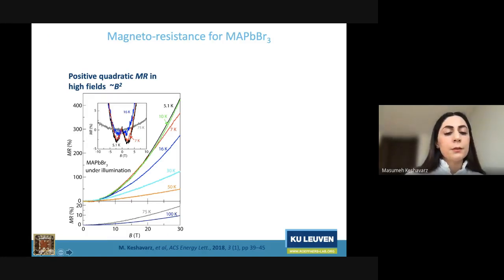Now let's look at the magnetoresistance as a function of field. In general, we measure the magnetoresistance for different temperatures. For methylammonium lead bromide, it is shown here, and we see this classical orbital effect, which is the quadratic behavior.